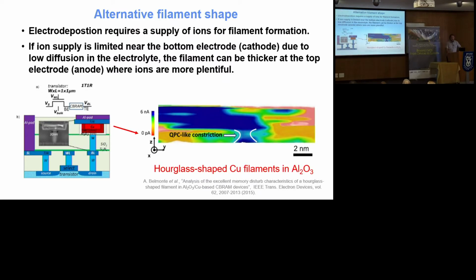My favorite is Attilio Belmonte's work showing how these hourglass-shaped filaments form in very thin layers of aluminum oxide, where you have a lot of copper, for example, available for electrodeposition near the copper top electrode, coupled with a lot of electrons available for the reduction near the bottom electrode. And you get an hourglass-shaped filament, which he has managed to image rather nicely there.